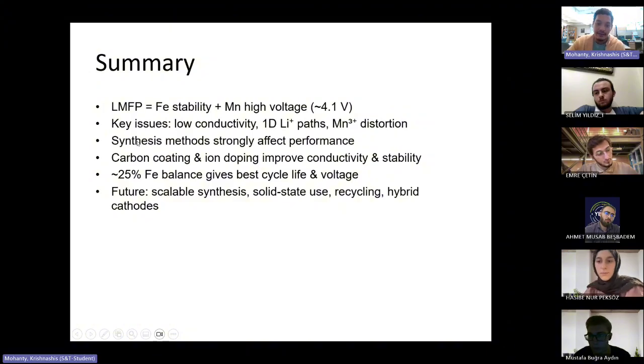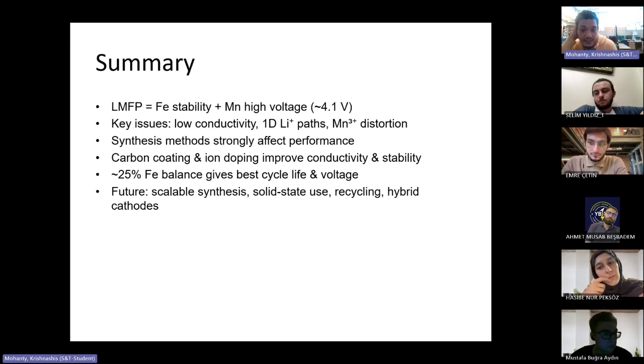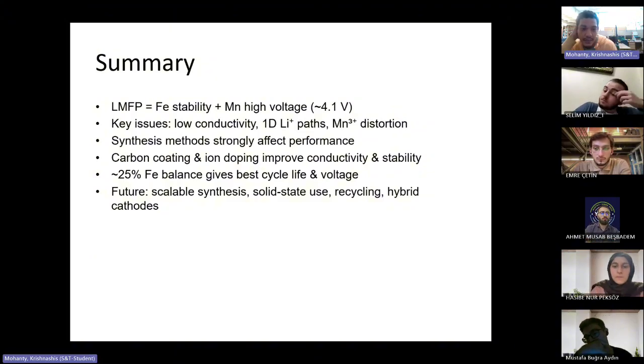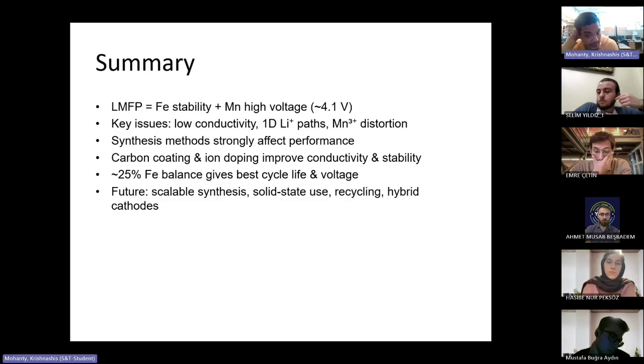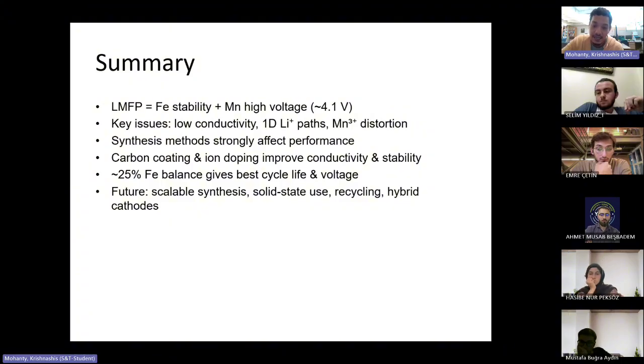Synthesis methods strongly affect performance. Carbon coating and ion doping improve conductivity and stability. As we read through different papers, papers have claimed a 25% iron balance gives the best cycle life and voltage, but because this is very recent research, claims have been all over the place. People claim 80% manganese is better. People claim 50% manganese is better. So it just comes down to the synthesis method itself and the right chemistry.